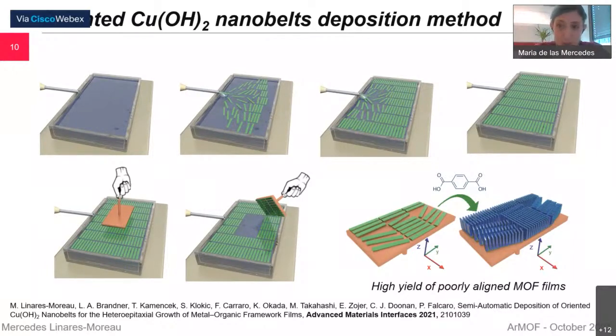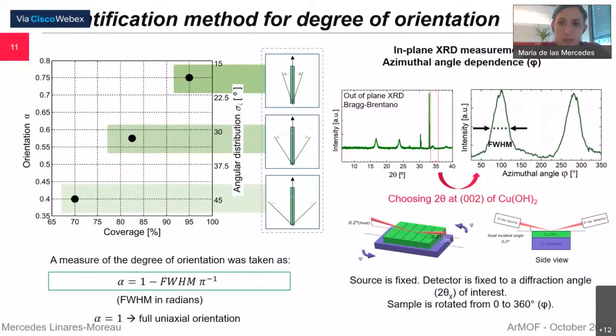So before I show these results, I want to quickly explain how we measure the degree of orientation of these films, because it's the parameter that we use to compare different samples. Based on the X-ray diffraction measurements from the normal out-of-plane Bragg-Brentano XRD, we select the 002 reflection of the copper hydroxide, which is around 34 degrees. Keeping the source and detector in that configuration, if you rotate the sample and collect the intensity, you get an azimuthal profile of the X-ray diffraction. If the sample was not oriented, you would get basically a flat line because the intensity would be the same for all the azimuthal angles, for all the in-plane angles of the sample.